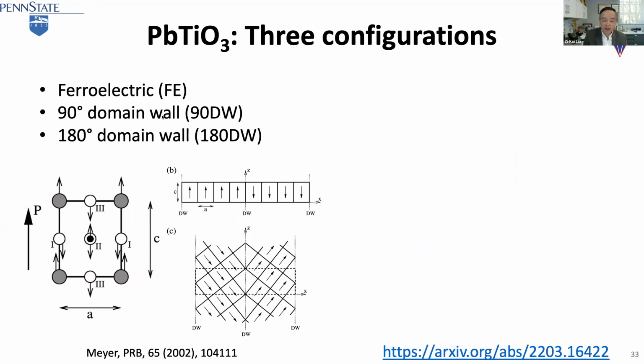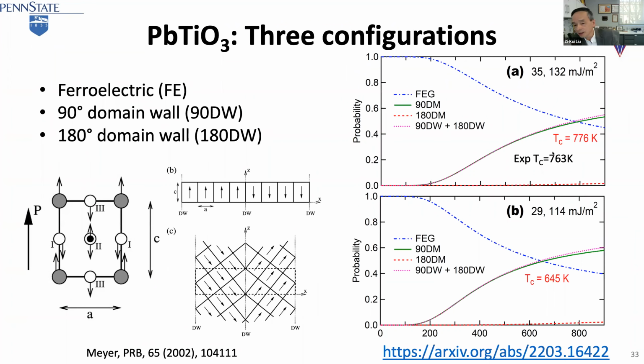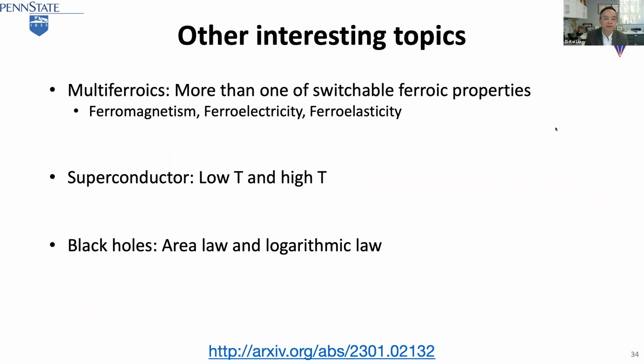And people calculate the energy. So this is the first one. This is 180 degree and 90 degree. The mixed one put together, we actually don't predict it. When we predict the transition, it remarkably agrees with experiments, only 13 degrees off. And this also uses 0 Kelvin energy only. If we include entropy, which we're working on now, we expect it to be even closer to the experiment.